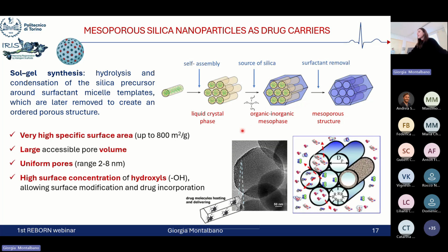So these materials represent a very strategic nanomaterial for the incorporation and release of different biomolecules and drugs, thanks to their really good characteristics, like the very high specific surface area, the large accessible pore volume with a diameter ranging between 2 and 8 nanometers, and also the high surface concentration of hydroxyl groups exposed on the surface that allow easier surface modification and drug incorporation.